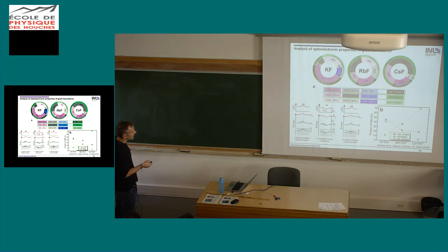So we look just at the outside ring. And we see that here in the KF case, we have a lot of grain boundaries that are negatively charged, a few uncharged, and also a lot positively charged. If we look at the rubidium one, the negatively charged part is smaller. We have uncharged and positively charged. And in the cesium one, we have a lot of uncharged ones, a few negatively and a few positively charged ones.